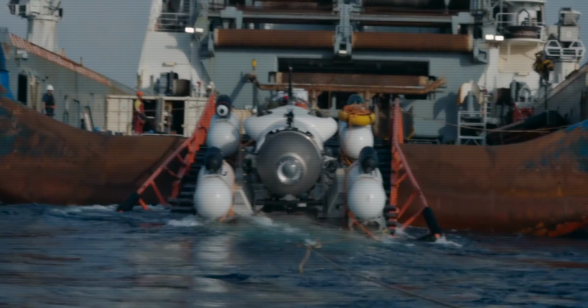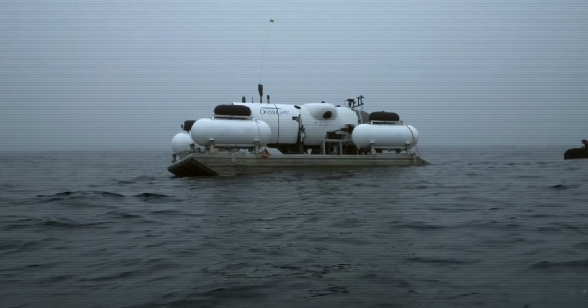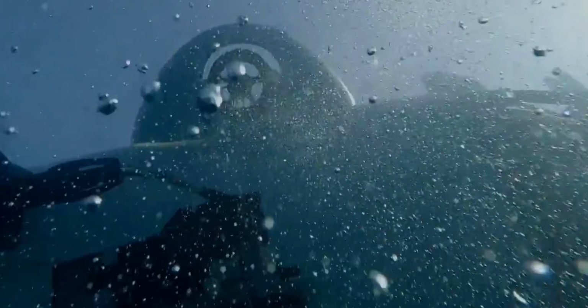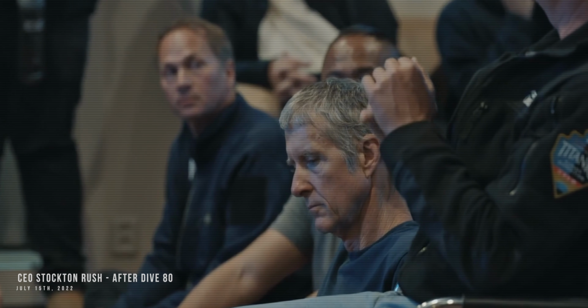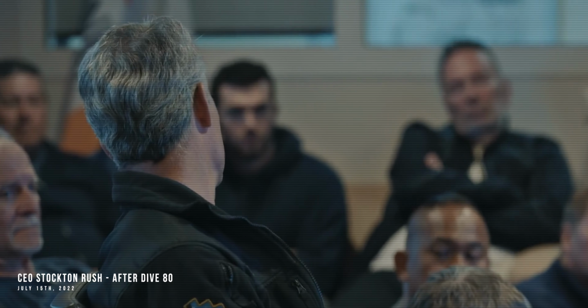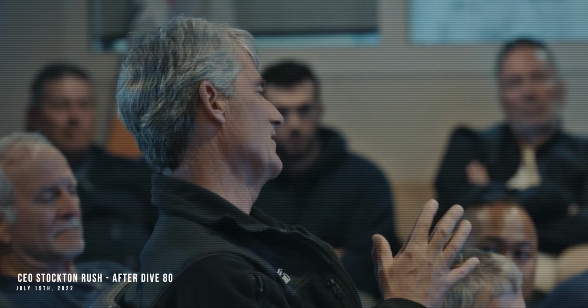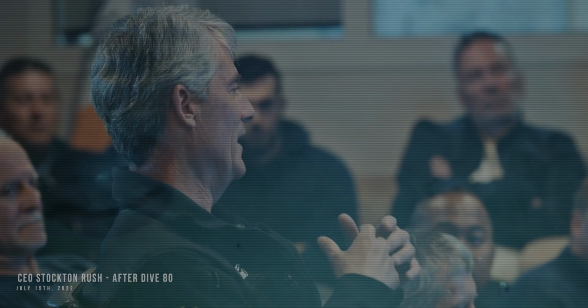On July 15, 2022, almost a year before the implosion, those aboard Titan heard a loud bang while ascending from Dive 80. OceanGate documented the event, but concluded that the pressure hull was simply settling into place, and operations continued. When we got to the surface, Scott was piloting. He heard a really loud bang, not a soothing sound. No. But on the surface, and as Tim and PH will attest, almost every deep diving sub makes a noise at some point. You have just similar shapes and metals that are expanding due to thermal interaction, due to pressure changes, and it's quite common to have a noise.